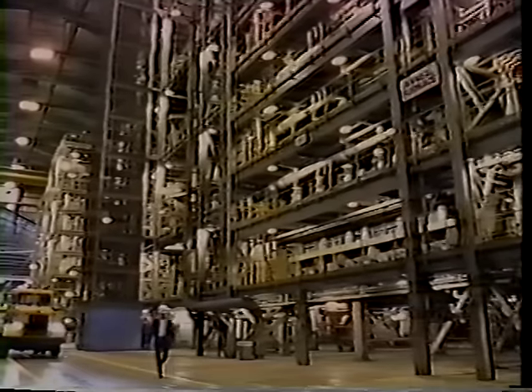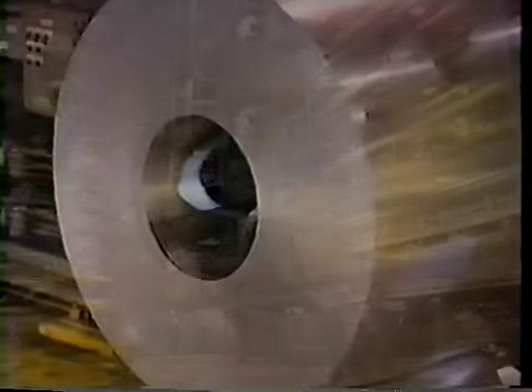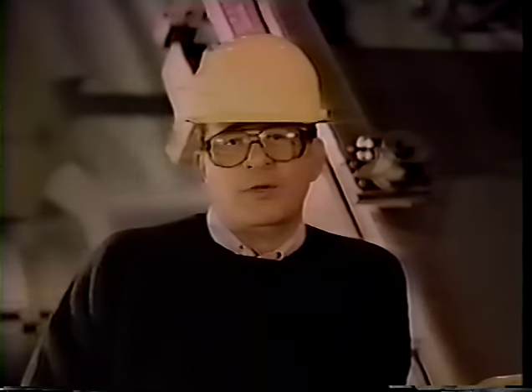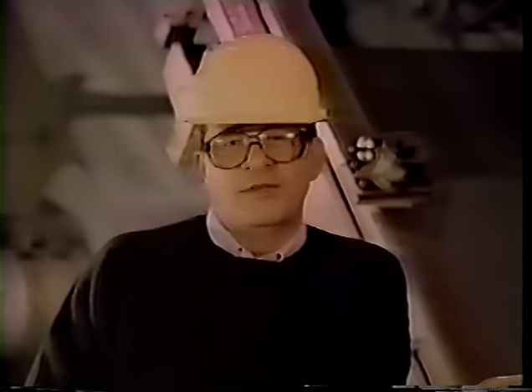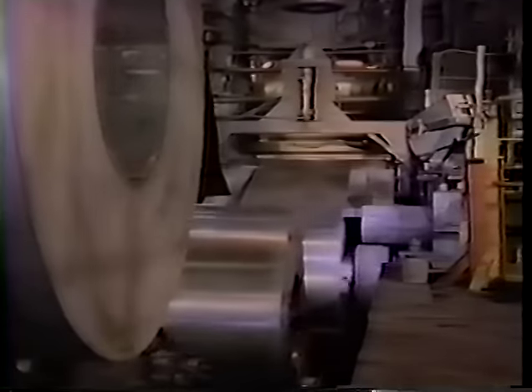The cold rolled steel enters the line and, after cleaning, moves through a succession of heating and cooling processes that lock in the metal structure and strength. This line simply is a high-speed replacement for batch annealing. We have the ability on this line, through our very accurate furnace and quenching controls, to produce a product that has consistent physical properties throughout the entire length of the coil. Once annealed, the steel is lightly cold rolled in a temper mill to improve its shape, surface, and mechanical properties.